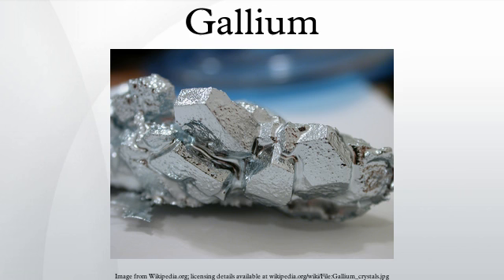Reducing Ga2O3 with elemental gallium in vacuum at 500 °C to 700 °C yields the dark brown gallium(I) oxide, Ga2O. Ga2O is a very strong reducing agent, capable of reducing H2SO4 to H2S. It disproportionates at 800 °C back to gallium and Ga2O3.